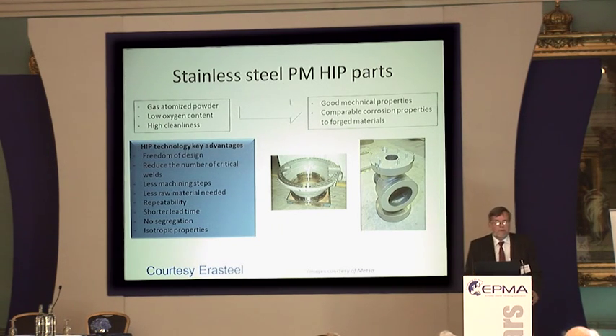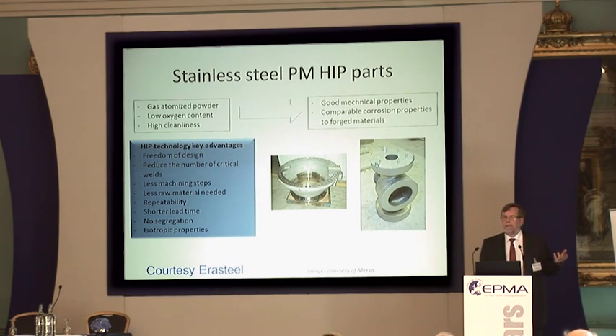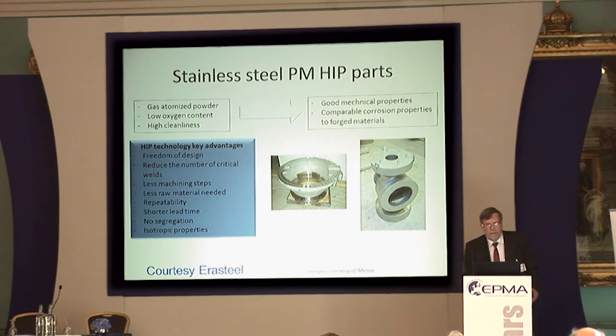So if you summarize, the powders now used are very much better than 20 years ago. For the same alloy system with the same designation, you have 2014 compared with something from 1980, you have improved properties, strongly improved functional material properties. You have low oxygen content, high cleanliness. This gives good mechanical properties, as good as, often better than, cast and forged. And I would like to say comparable, but often better corrosion properties to forged materials.